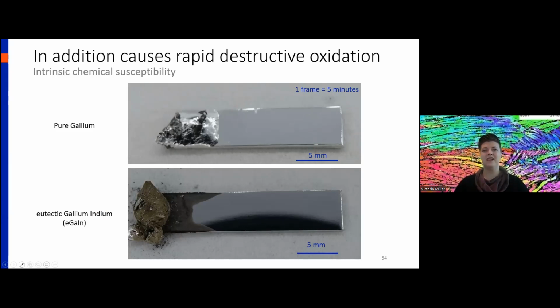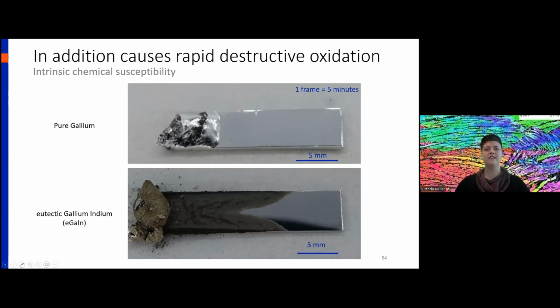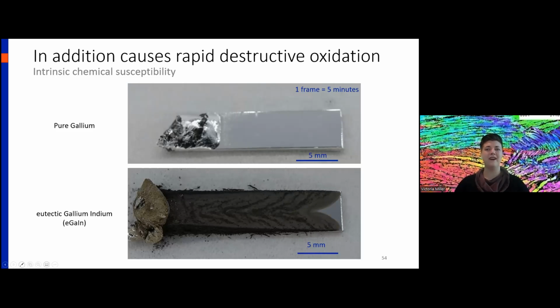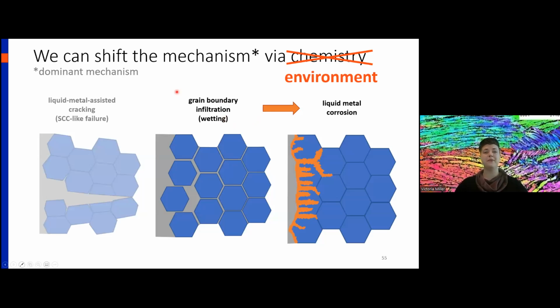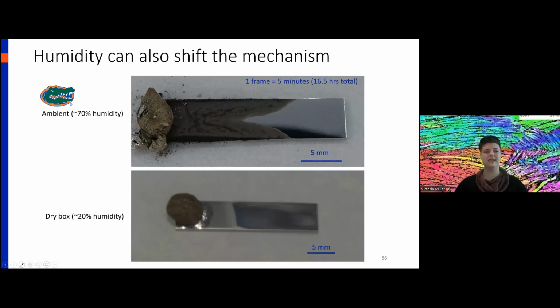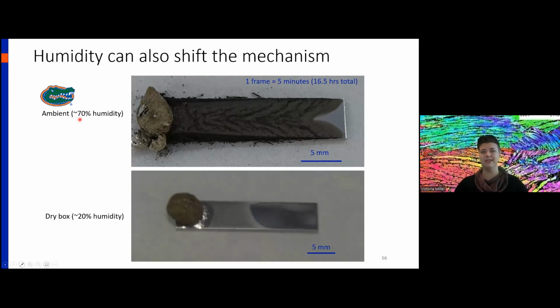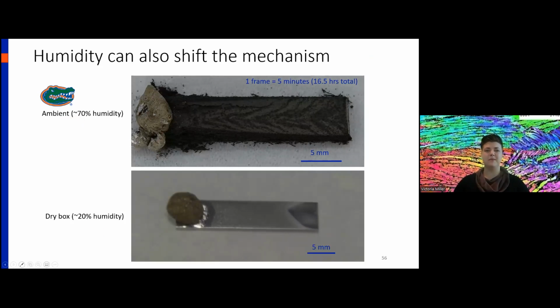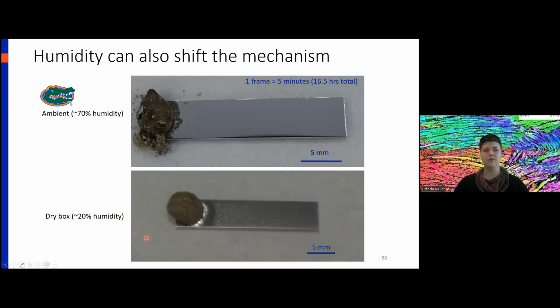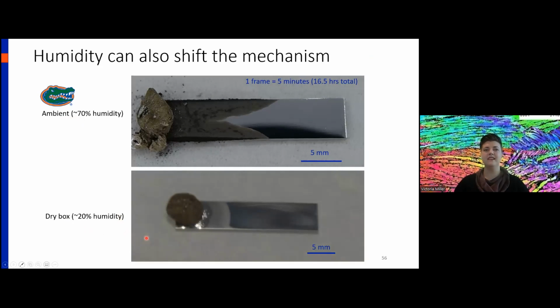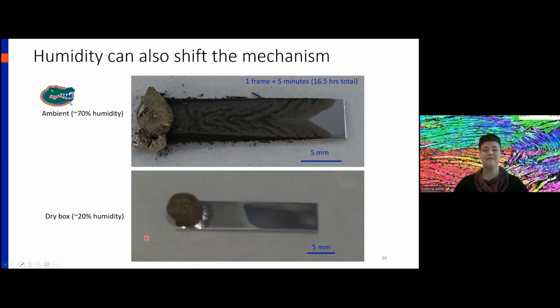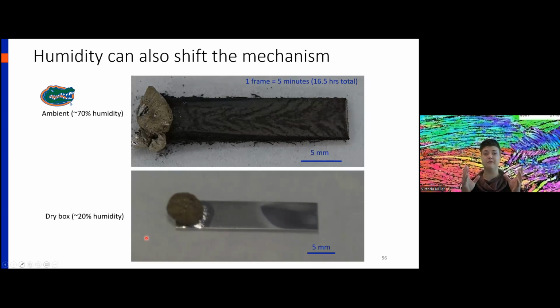The other interesting thing is that we can shift the mechanism via environment as well. So we can shift from grain boundary wetting to liquid metal corrosion just by modifying the humidity. So this is that same GIF that I just showed. This is Florida ambient humidity, so about 70% in the lab, versus in a dry box, we ran the same experiment. So at about 20% humidity, you get grain boundary wetting, whereas at 70% humidity, you get oxidation corrosion. So we can shift what mechanism is active by modifying the environment.